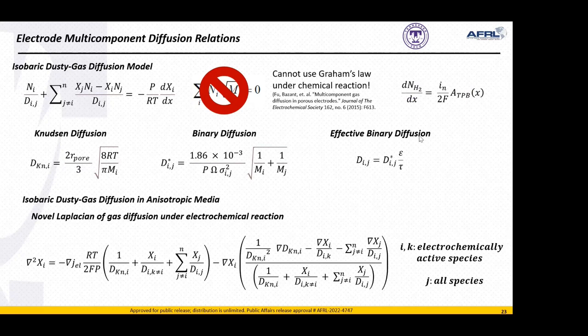Instead, what we have done is impose the constraint that the local flux, and here I've just defined the local flux of hydrogen, is going to be equal to my local current density divided by 2 multiplied by Faraday's number, and then multiplied by the local area of the triple phase boundary. And doing this, you can be referred to the full derivation within the dissertation text. But we have defined this novel Laplacian of gas diffusion under electrochemical reaction. And this is in the case of isobaric diffusion in anisotropic media. So this Knudsen diffusion term here and here can again change because my porosity can change throughout the thickness of the electrode.